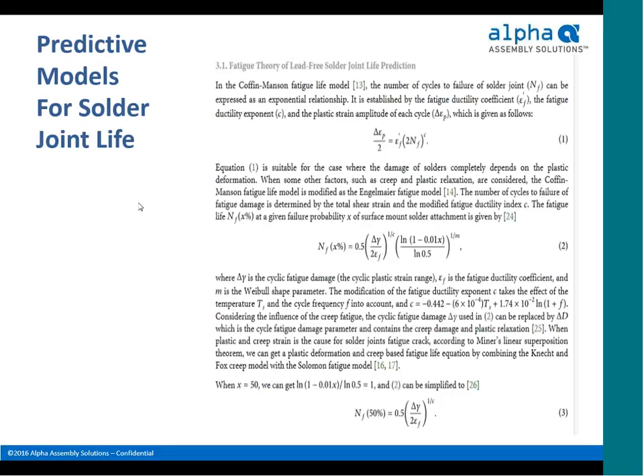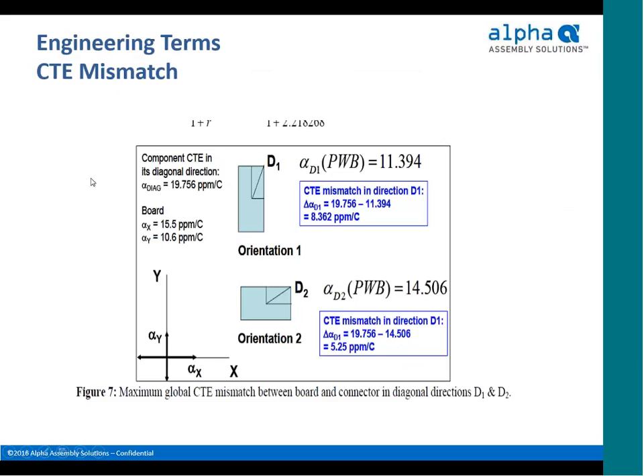One thing we do know is that they've changed. The stress and strain that's applied to tin lead and lead free that causes failures is different between the alloys. So there's a lot of work in trying to characterize and develop these predictive models for the lead free side as well. It gives you an idea here that all of your forces are really vectors, and they act in a number of different directions depending on, as you apply temperature, how much expansion you get from different materials and the junction of those two materials.